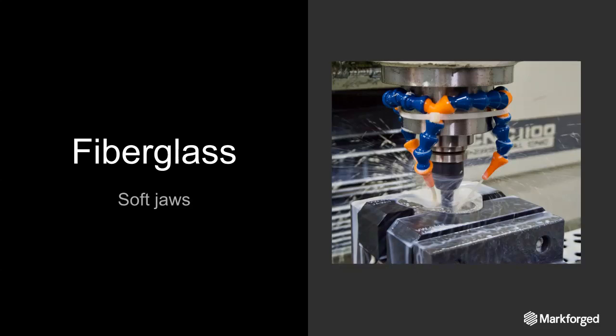Here's an example of a fiberglass reinforced soft jaw in action. Custom soft jaws are a really good way to precisely hold irregularly shaped parts when you want to machine them. When Onyx is reinforced with fiberglass, the 3D printed jaws are stiff enough to keep the part from moving around when you're machining it, but soft enough to have a non-marring surface so you don't mess up the part from the clamping force. In this particular case, the jaws are holding a needle bearing housing, which is undergoing a facing operation on the mill.